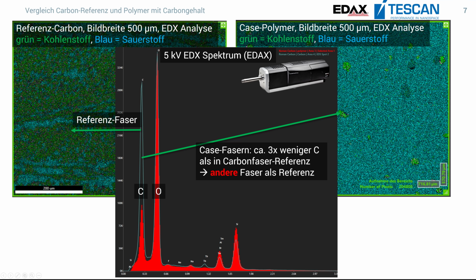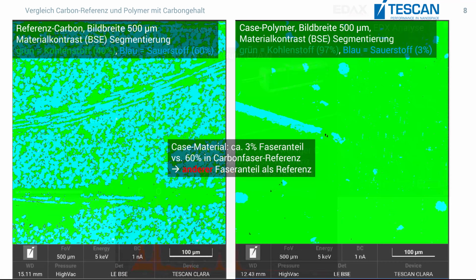What I found interesting is that they even compared the carbon fiber itself. The carbon fiber reference from the left has about 3 times higher carbon density than the carbon fiber on the right, which basically just indicates that it's a lower density of carbon compared through the different carbon fiber materials. Doesn't necessarily mean a lot, but if we switch to the next view, to the EDX analysis, then you can spot that the right side only features about 3% of carbon fibers inside a polymer, whereas we have about, as expected, 60% carbon fiber on the left.